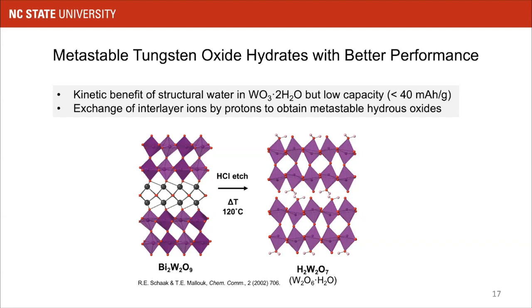One route of doing this is to take high temperature solid state materials and exchange their interlayer ions by protons. One approach is to take this bismuth tungsten oxide material, expose it to acid, and you form a material that looks very similar to what we were working with before, except now the water networks are separated from each other by every two tungsten oxide layers. This is a different way of writing this formula. You can think of it as hydrogen tungstate or W2O6·H2O, which shows the relationship to what we were working with before.